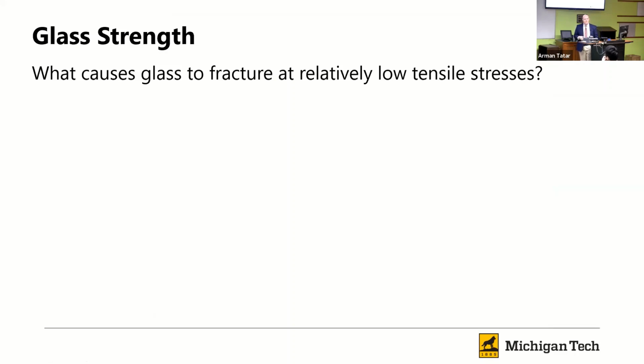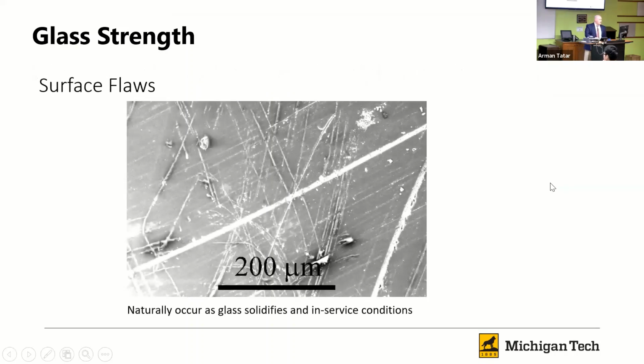So let's talk about glass strength in general, and what is the reason why it fails at such a relatively low tensile stress. And the primary reason is that all over the surface of glass, we have these microscopic flaws in the surface, and those can be caused naturally as the glass solidifies. They also can be changed or modified or added through in-service conditions. That could just be from the environment interacting with the glass. It could be cleaning or touching or otherwise, all sorts of ways.